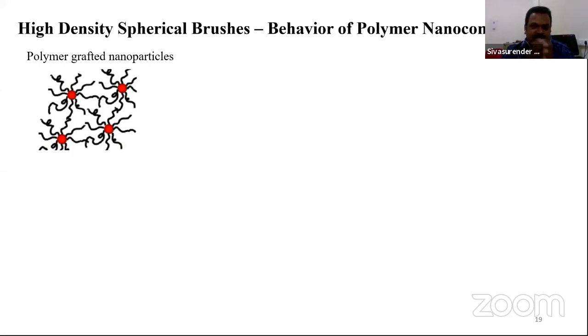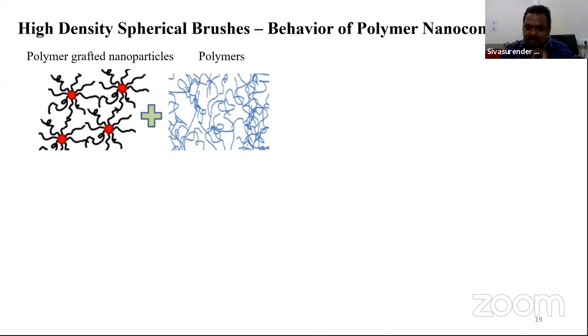And that's what we have done extensively, where we have used nanoparticles and grafted polymer chains, as I've indicated, via these black chains attached to these red spheres. These red spheres are nanoparticles with diameters of the order of 3 to 5 nanometers. And these chains are really long. So you could create such a very densely brushed system and then mix them with polymers, right?